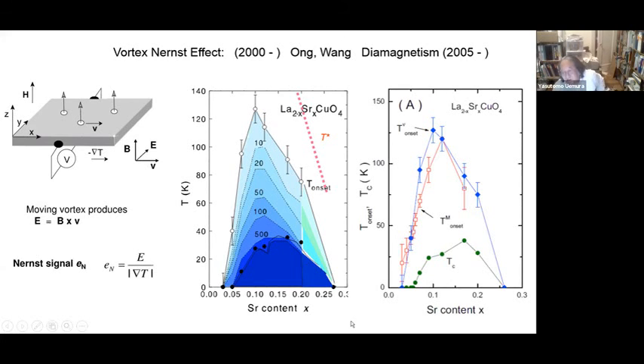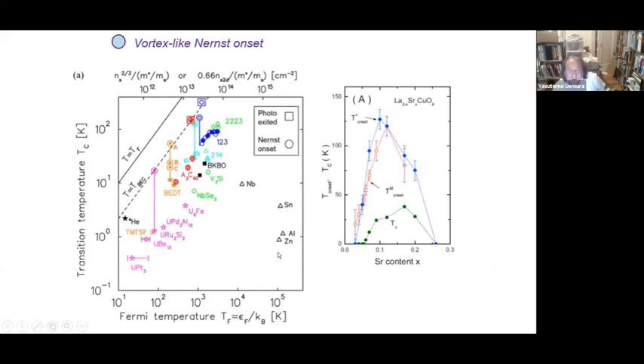So the same interesting thing happens also in the diamagnetic response. And again, this response onset temperature is about the same and about a factor of 4 higher than TC. So with this factor of 4 or 5 higher than TC, if we would like to plot the Nernst onset temperature, for example, for this particular cuprate, you can just use the μSR measured superfluid density for the horizontal axis and the onset temperature of the Nernst effect for the vertical axis. And if you do so, the point for underdoped 214 is here. You can also plot a point for underdoped 123, and it becomes here.